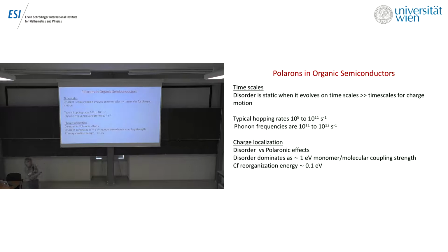This point was alluded to yesterday as well: if you've got static disorder, that simply means that the disorder is evolving on much longer timescales than the timescales you need to get the charges out of the device. Typical hopping rates are of inverse nanoseconds and higher. Phonon frequencies, on the other hand, are much higher. They're typically terahertz. And so there is a timescale difference.